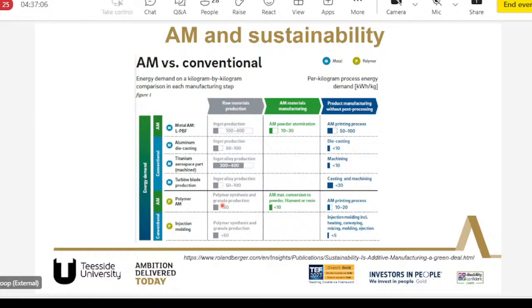In terms of polymer as well, the same. The ingot production of the major synthesis is around 50 kilowatt hour per kg. Then you convert it into resin or powder or a filament. Again, it consumes 10 kilowatt hour per kg. Then it goes to a printing process where it consumes around 10 to 20 kilowatt hour per kg. So again, you can start splitting the stages, and then you can understand how AM also contributes towards this sort